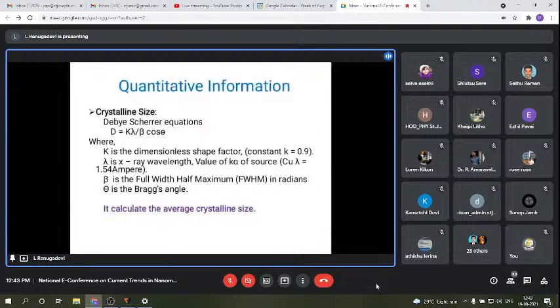This is the quantitative information from the XRD: the crystallite size by the Scherrer equation, D equals K lambda divided by beta cos theta. We have already known this equation. K is the dimensionless shape factor and its value is 0.9. Lambda is the wavelength, 1.54 angstrom. Beta is the full width at half maximum in radians. Theta is the Bragg angle. Using this formula, we have calculated the average crystallite size.